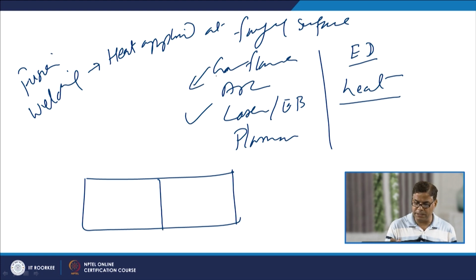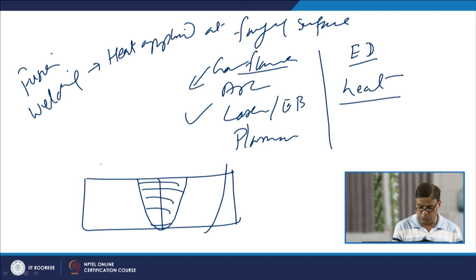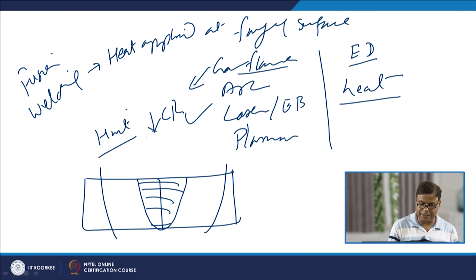Like low energy density processes such as gas welding, it will be required to supply more amount of heat. So, the weld metal fused zone size is more, the heat affected zone size is more, and because of the high heat input we get lower cooling rates.